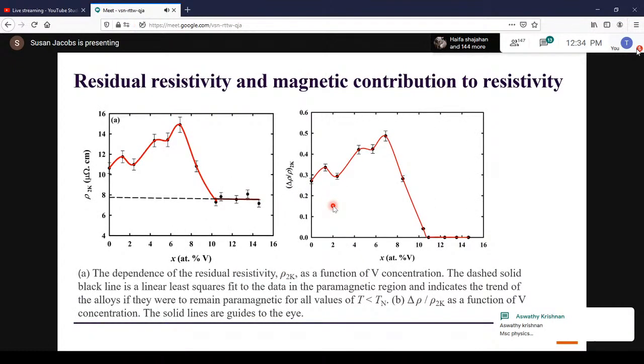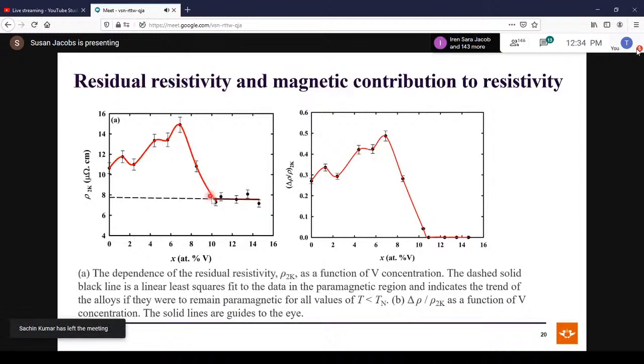We can also get other information. If you look at the residual resistivity and the magnetic contribution to resistivity. Residual resistivity is just resistivity at the lowest temperature. In this measurement, it was 2 Kelvin. If you look at the trend, you will see it increases up to about 6.9 and then sharply decreases through the critical concentration and remains flat in the paramagnetic region.